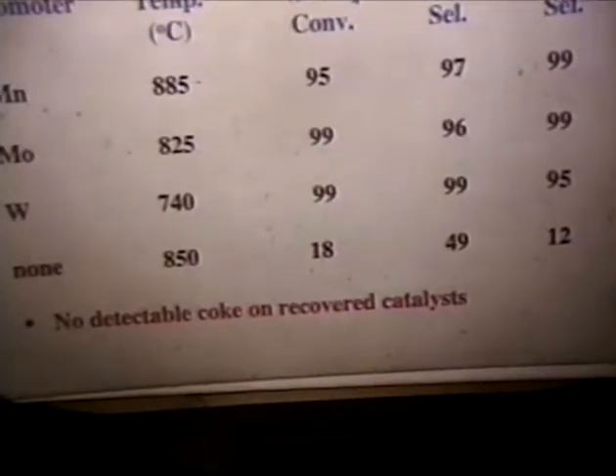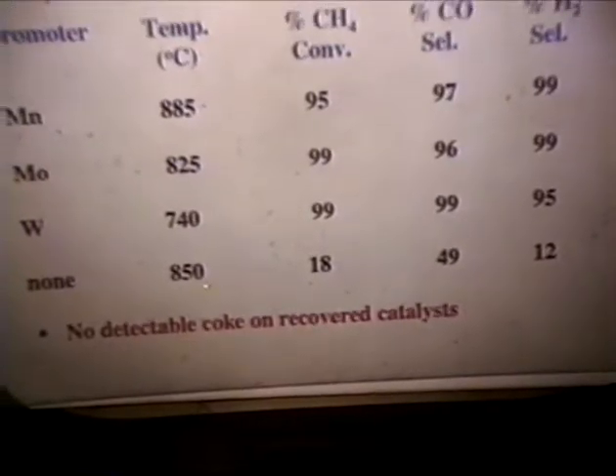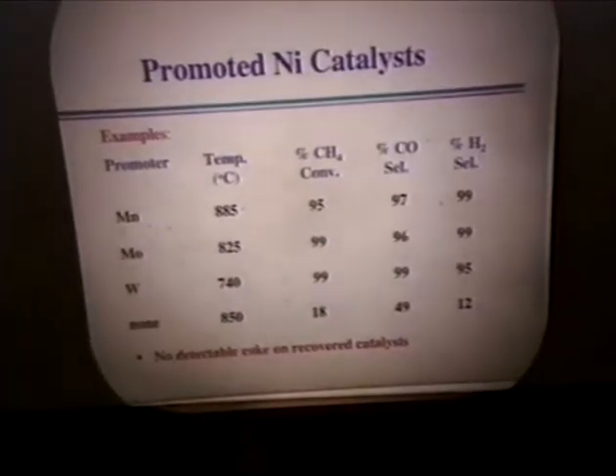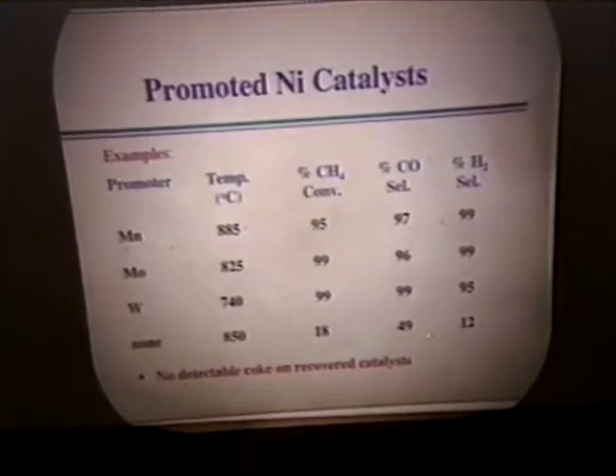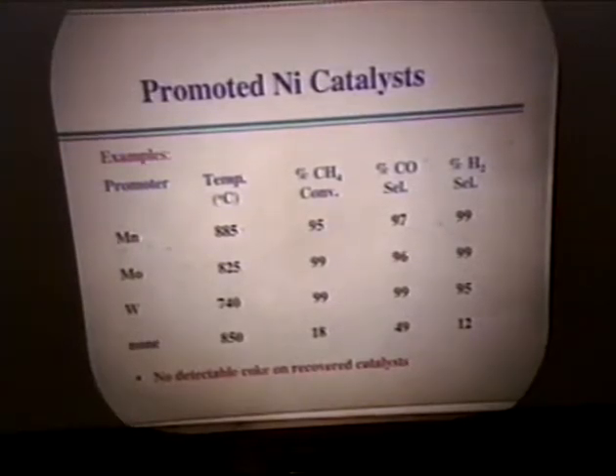So comparative data is shown here. If we have no promoter present, our conversions and selectivities are fairly low, but adding in promoters of manganese, molybdenum, and tungsten, we're able to achieve numbers in the 90s. And you'll see that we were not able to measure any detectable coke by TGA analysis.